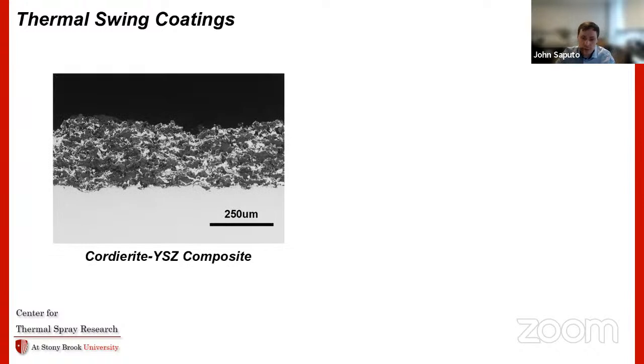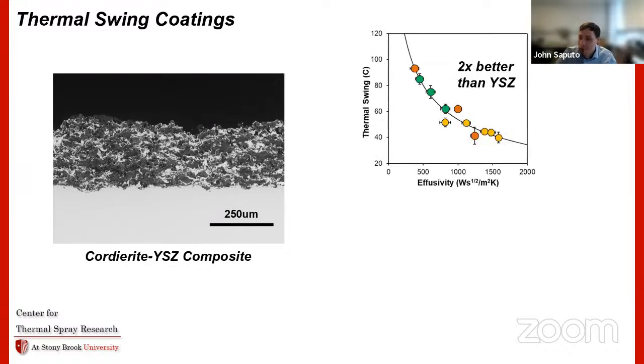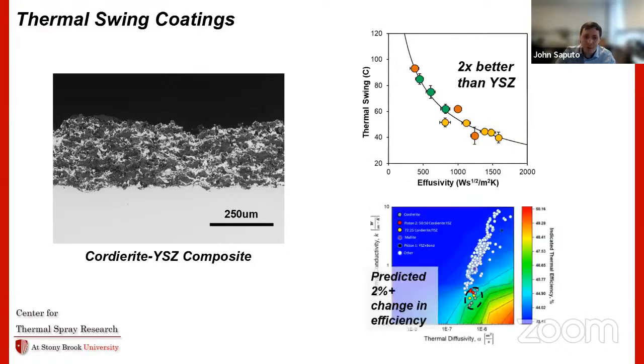This is that cordierite zirconia composite, the same thing that I showed you, the blue, nice temperature following coating that we had before. We know that this performs in laboratory tests by all metrics about 2 times better than YSZ. It's predicted to fall into a range where it should get about 2% change in engine efficiency based on all these simulations. It's got a conductivity of about half that of zirconia. So by all metrics, this thing should be a good engine coating material.